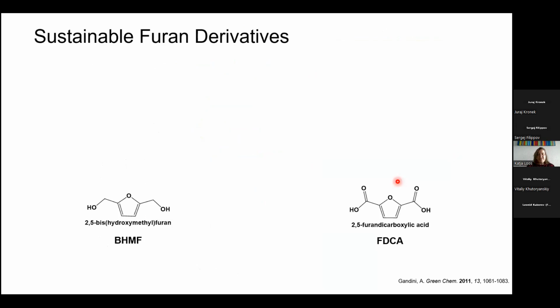So the monomers that we use are the furan-based diol and the furan-based diacid. And I'm pretty sure you hear a lot about FDCA, because this is the monomer also of PEF. And a lot of people polymerize FDCA. Now this diol, BHMF, is not very stable, because of the position of the two hydroxy groups, it's not very stable in melt polycondensations. That's why you find hardly any reports of BHMF-based polyesters or polyamides.